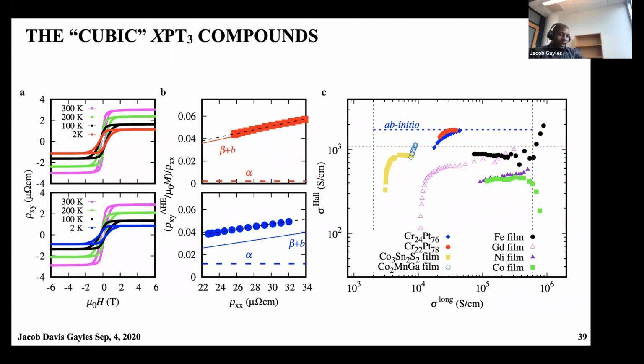So yeah, because we were in Claudia's group, of course, the films group, we had some a priori knowledge that the strain can change things. If it's a cubic system, it can make it tetragonal. So we tried to grow it so that the three crystal axes are growing out. So there is strain, but it's equal on all crystal axes. So the 111 orientation is out of the plane, yeah. So there's no strain in this case. The strain, I believe, would not change it drastically.